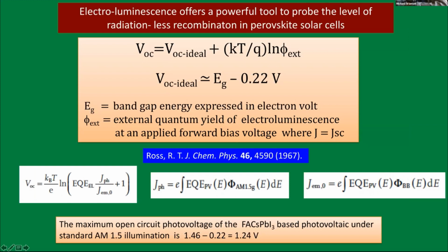And so here's a famous equation that links the external quantum efficiency of luminescence to the voltage. And the ideal voltage, that's the radiative limit, which you can calculate. It's not so hard. And there's a paper by Ross who introduced it. We ourselves have published several papers. But at the end of the day, if you say my cell is good and I have very few defects, then you should almost see with your naked eye the luminescence coming out. By contrast, if you have a photovoltaic material that doesn't luminesce at all, then you have to worry. Then I would go down to low temperature, and if it still doesn't luminesce, throw it away. It will not be a good photovoltaic material.